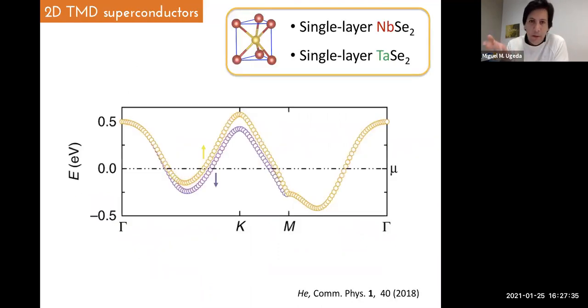Okay, so for these experiments, I will today focus on 2D materials. We have used 2D materials for our experiments, single layers of niobium diselenide and single layers of tantalum diselenide. The reason for that is that these two materials have a very similar band structure, the one I show you here. So basically in the single layer limit, these two materials only have one band involved in superconductivity. There is only one band that crosses the Fermi level. As you see here, it has a d character band, so basically it comes from the transition metal element.